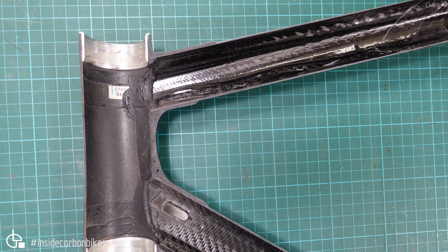Often you see wear on the steerer tube, and that's often when the bearings aren't concentric, and so it puts an extra load basically on one face of the steerer tube, because the steerer is trying to be concentric, but if the bearings aren't, then you're going to have problems. So a little bit of extra adhesive spew out through here, but no voids through this lug junction through there. But that all looks pretty good.